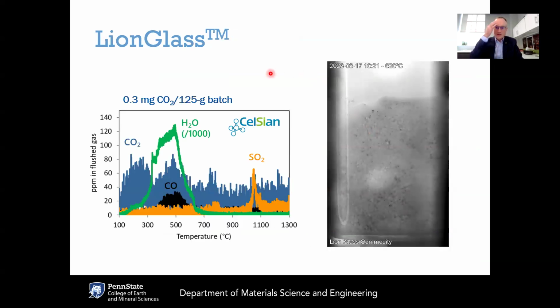Now, if we compare this to LionGlass, this is the same type of setup for LionGlass, the same size batch. You can see the gas chromatography results on the left. First thing to note is that this is the actual CO2 concentration, not divided by 100. You can see that this is staying basically at noise levels. So it's just atmospheric CO2 as well as any trace carbonate impurities that happen to be in the batch materials. But if you integrate all this noise, what you get is 0.3 milligrams of CO2.